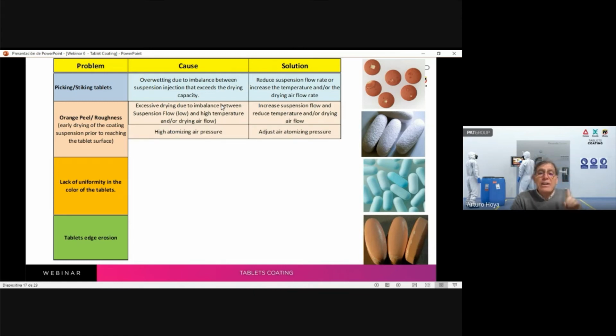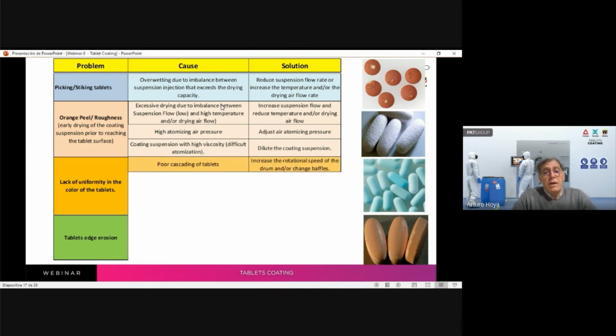Another possibility is high atomization air pressure. If the air pressure is very high, the drops are very tiny, and the very tiny drops dry before reaching the surface of the tablet, and impact in a dry state, fixing on the surface and producing this roughness. So all you have to do is adjust the pressure. Coating suspension with high viscosity makes atomization difficult and produces orange peel, so dilute the coating suspension. For the lack of uniformity, poor cascading of the tablet bed, increase the rotational speed. It is a very simple way.